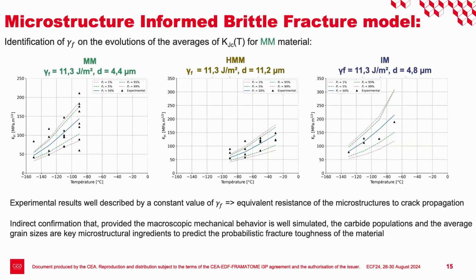Finally, the results of the model. The points are the experimental results for the MM, HMM, and IM materials. And the curves are the Weibull probability solution of your model. What you can see is that if you use the correct mechanical behavior, the correct distribution of carbides, and the correct average grain size of each material, you can describe all the experimental results with only one constant value of the energy parameter, which is the last free parameter of the model. So we have only one parameter that is kept constant. Basically, this means that your microstructures have the same crack-resistance property. And with only one constant parameter, you can describe experimental results that were quite different from one material to another.